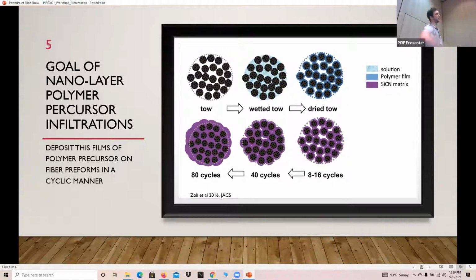And you can see this is an image from that paper looking at basically diluting what we're using, either toluene. They were using Ceraset and toluene. We're looking at SMP10 in hexane as the dilution agent, solvent rather. And basically we're putting on really thin layers using a 120 microliter drop onto a surface, and that wets out evenly across all fibers. Essentially we're looking at getting a 100 nanometer to 500 nanometer layer of silicon carbide per layer as we build up the matrix.